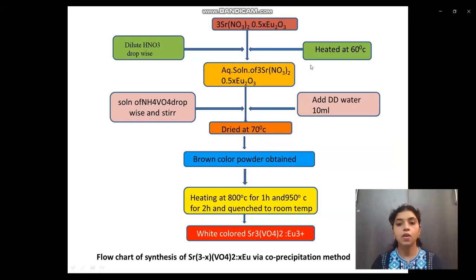Then it is dried at 70 degrees centigrade on a hot plate. Brown colored powder was obtained, and this powder was heated at 800 degrees centigrade for 1 hour and 950 degrees centigrade for 2 hours and then quenched to room temperature. Finally, the white colored product was obtained.